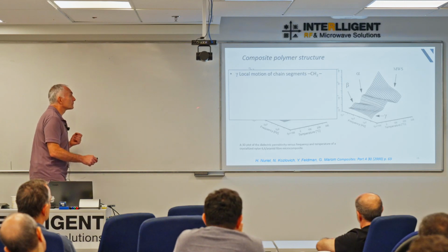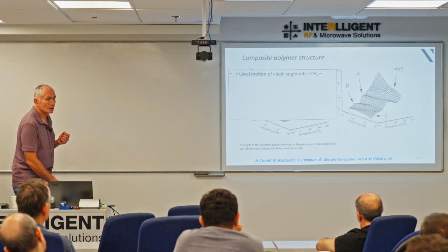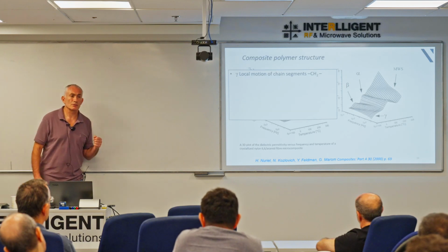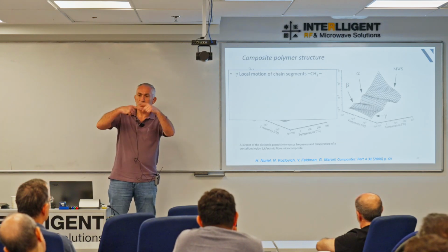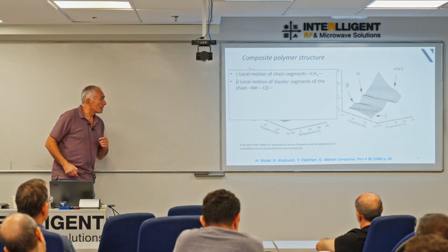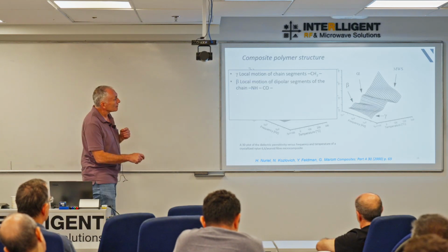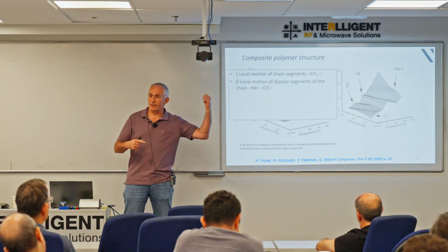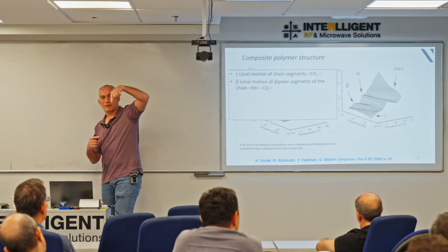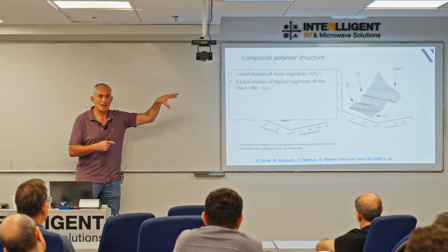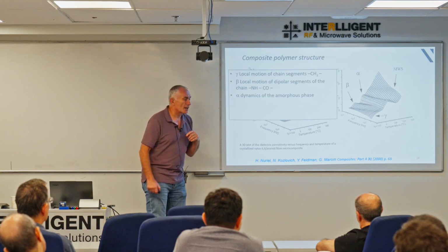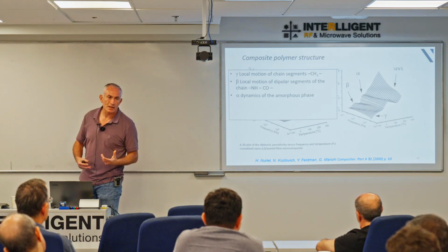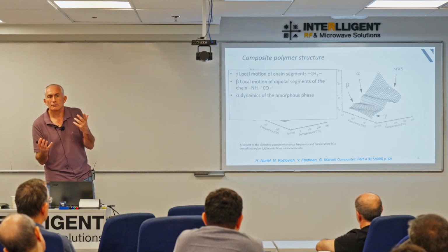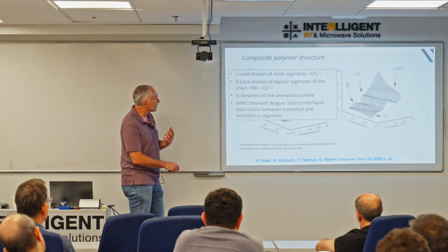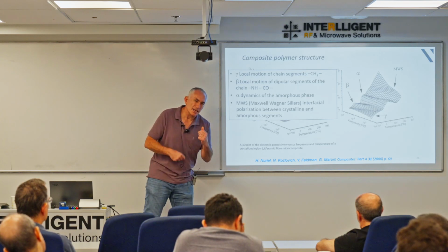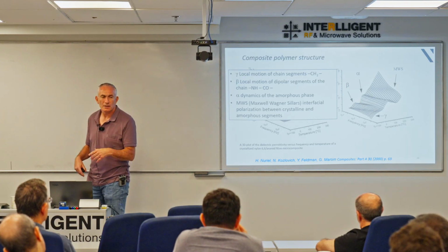So what we got? Gamma, this very high frequency process, that's basically local chain motions, inside the chain segments, things revolving around each other. Beta, dipolar segments. You may have a particular dipole inside, and in fact we're going to see one on Viton. That can also revolve. That can also change. So we can see that do something. Alpha, the dynamics of the amorphous phase itself, the glass-forming nature of many, many polymers. How this is especially affected if they cross-link, and how that will change. And the Maxwell-Wagner-Sillars, this one, is interfaces between different compositions inside the polymer.